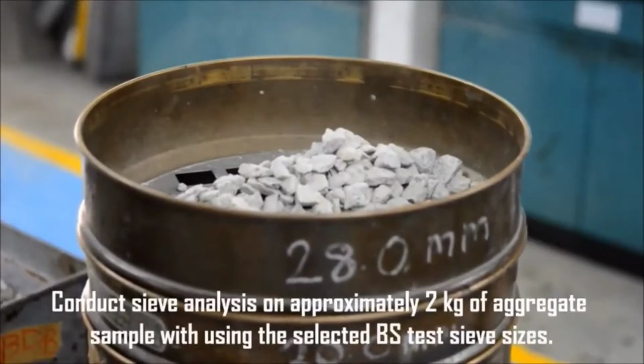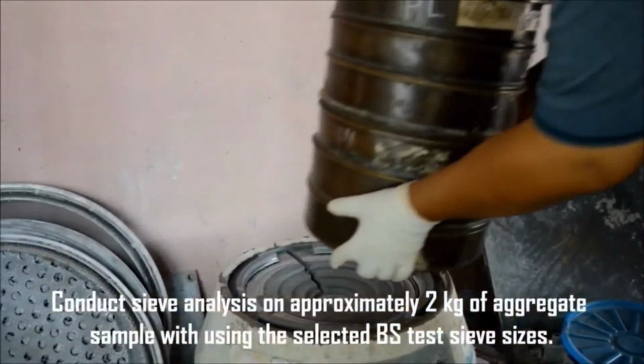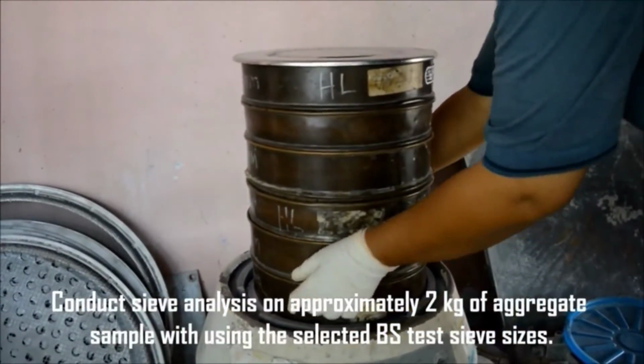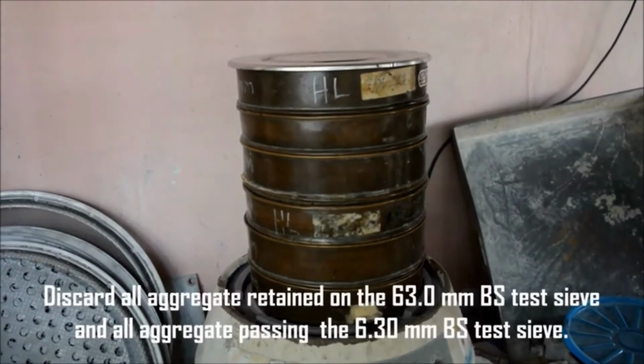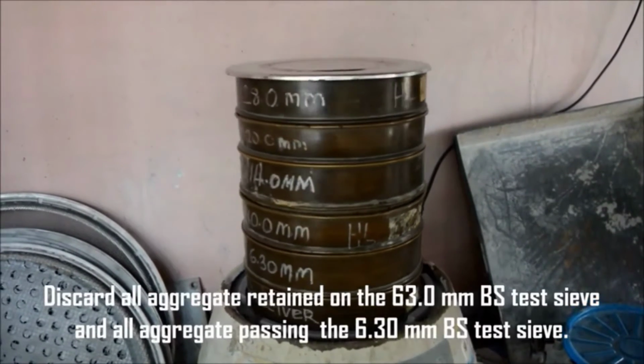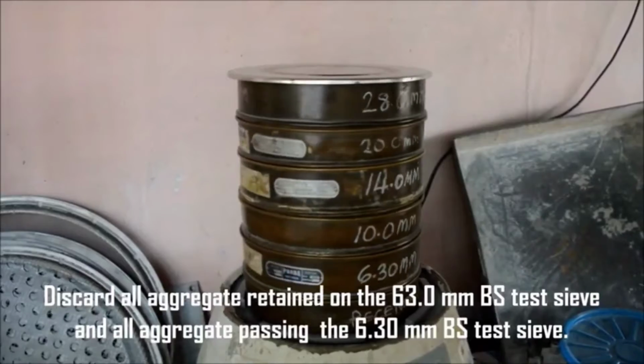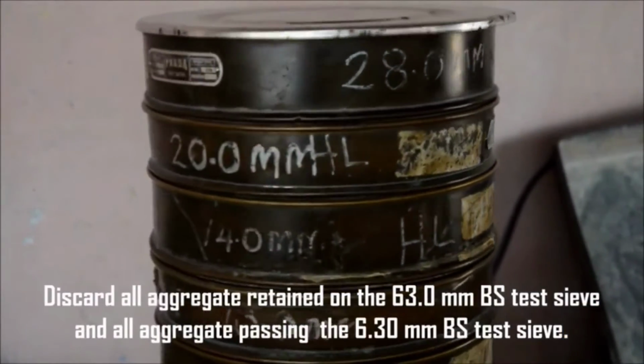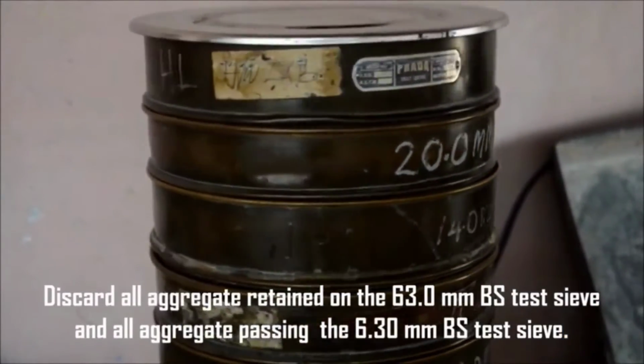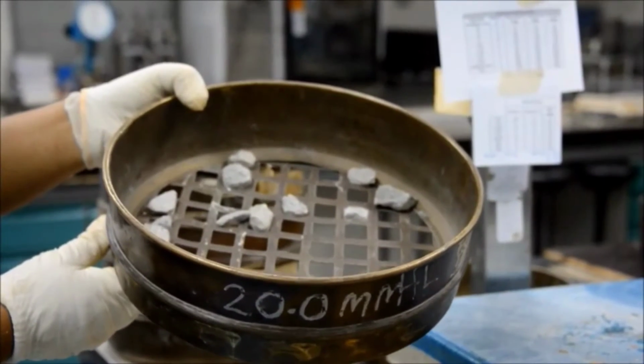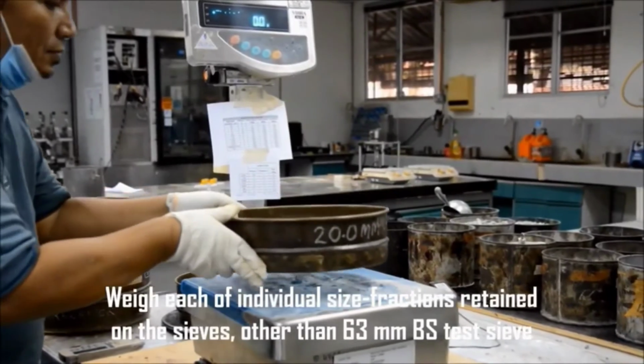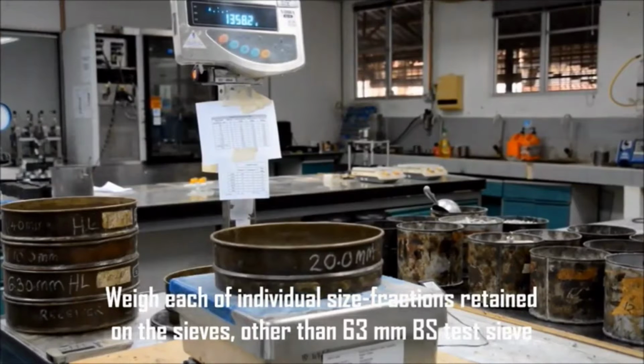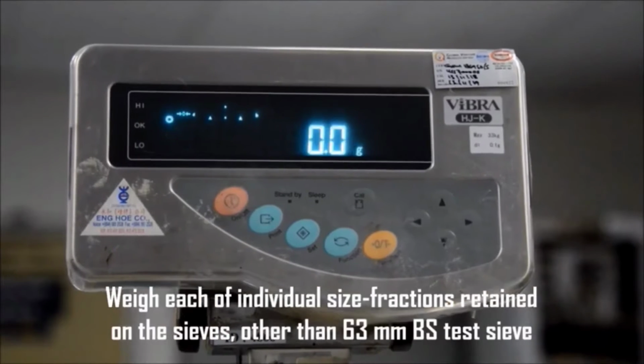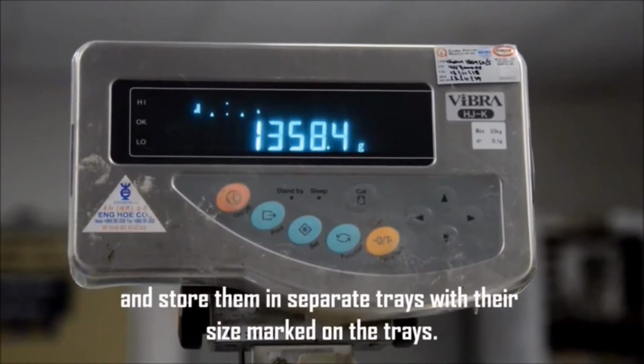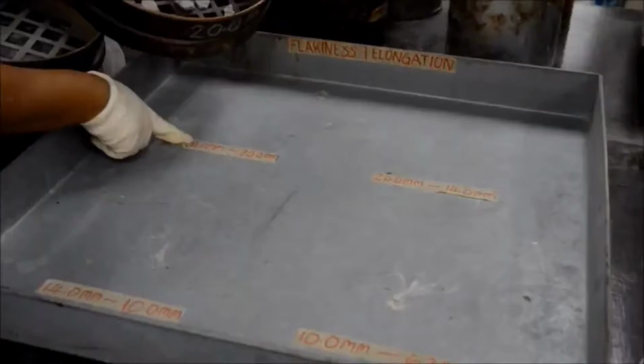Conduct sieve analysis on approximately 2 kg of aggregate sample, using the selected BS test sieve sizes. Discard all aggregate retained on the 63.0 mm BS test sieve, and all aggregate passing the 6.30 mm BS test sieve. Weigh each of individual size fractions retained on the sieves, other than 63 mm BS test sieve, and store them in separate trays, with their size marked on the trays.